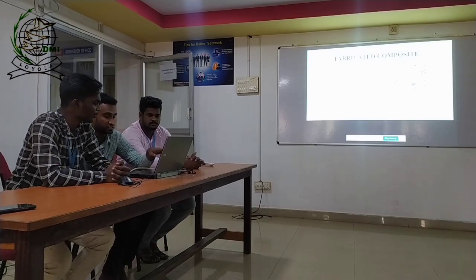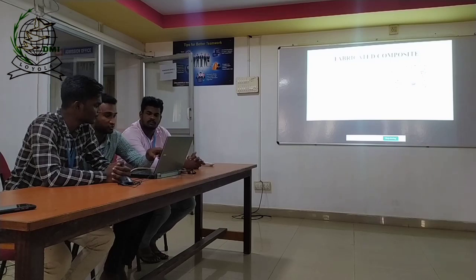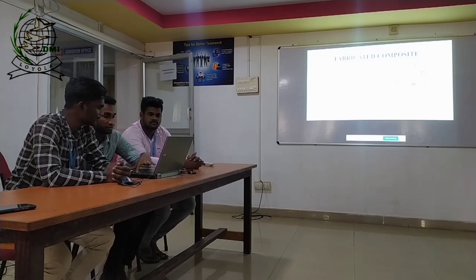Here, this is the outcome of the fabricated sample. Towards the right is the pure magnesium sample, and towards the left is the sample which has the presence of B4C. So, as we mentioned, we used a stir casting method to fabricate this material. This is a fabricated sample.